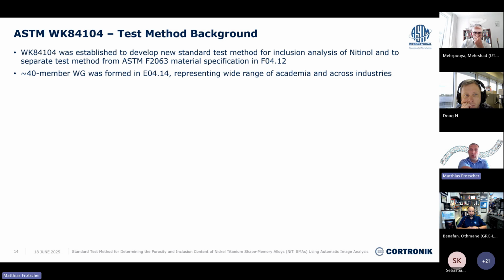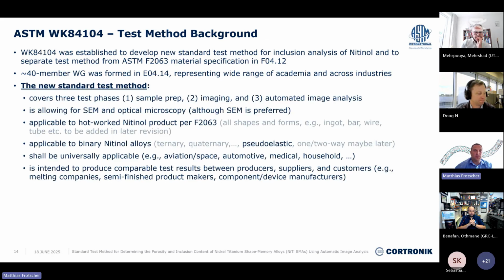We established a new working group at ASTM in E04.14 on quantitative metallography, and this is a cross-industry and academia team, and not limited to medical, as the new test method is supposed to be universally applicable. So Doug, you guys will be able to use it too for your applications once it's available. And the new method consists of 3 distinct phases. So we are trying to cover the sample prep phase, the imaging phase, and also the automatic image analysis.